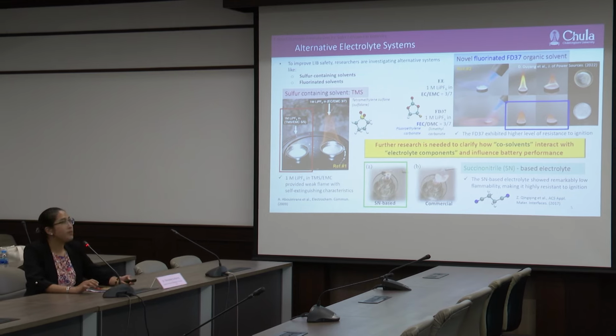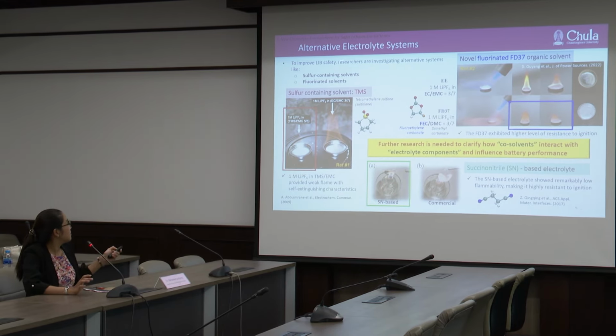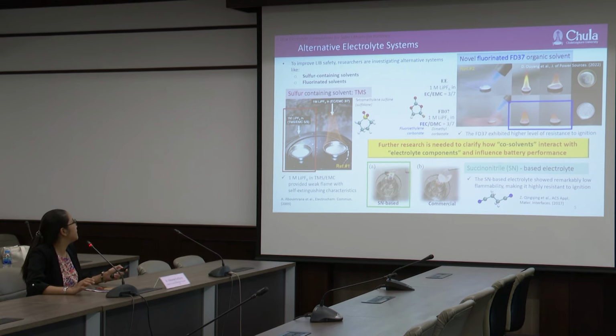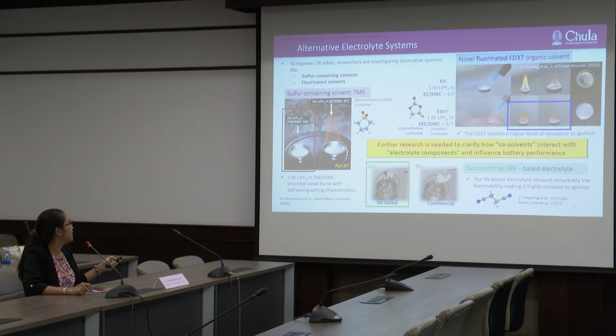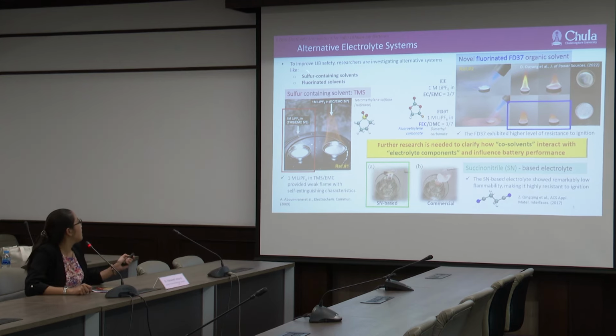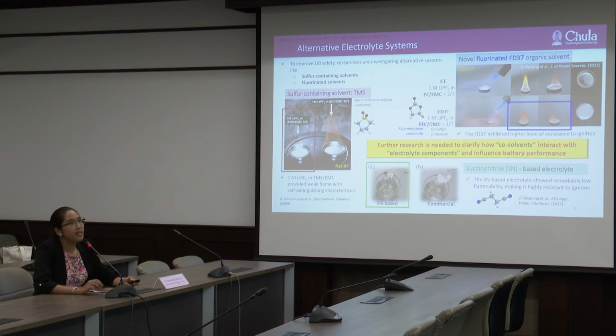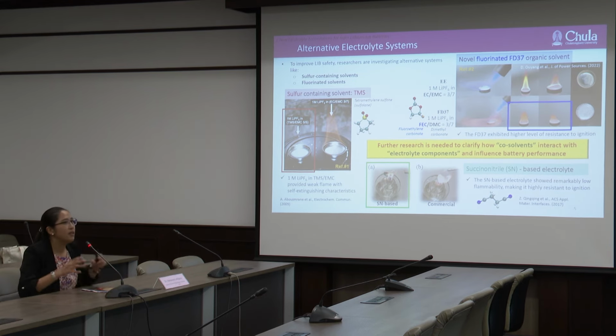To improve lithium-ion battery electrolyte, researchers are investigating alternative systems like sulfur-containing solvent. For example, here mixed sulfolane in the carbonate-based solvent, and also fluorinated solvent like fluorinated FD37. It is a mixture between fluoroethylene carbonate with dimethyl carbonate. Unfortunately, further research is needed to clarify how these co-solvents interact with other compositions and influence the battery performance.